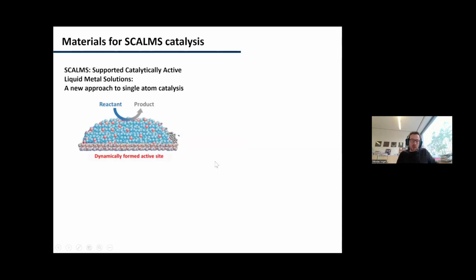Good. So why bother? Here's an example about SCALMS catalysis, which stands for Supported Catalytically Active Liquid Metal Solutions. So it's a new type of catalyst that's being developed here at our university, and that, in a sense, uses a particle droplet. So it's formed from a liquid metal solution, typically gallium, where you dissolve active species. And these active molecular or atomic species, platinum, palladium, and so on, they act as single-atom catalysts, and because of the dynamic nature, they can disappear, come to the interface and disappear again, and that changes, in a sense, the catalytic conditions, reduces coking, creates higher selectivity, and so on and so forth.